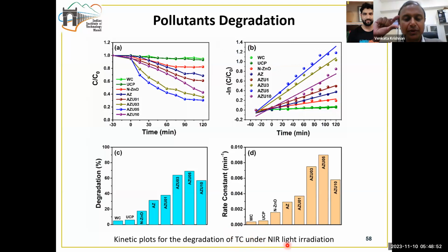We have a solar simulator. We blocked the visible light and the UV light using a thick bandpass filter, which lets only the NIR light pass through for the photocatalytic degradation of this tetracycline. And we found that one of the samples, which is the AZU05, gave the best result, which shows that it's the upconversion nanoparticle which is the main player of the reaction. Whereas the gold and ZnO, they have a lesser role, which we will be seeing. They don't have a direct role, but obviously they have an indirect role, which we will examine in the mechanism part. So nevertheless, the upconversion nanoparticle is able to do this photocatalytic conversion. That's the bottom line.